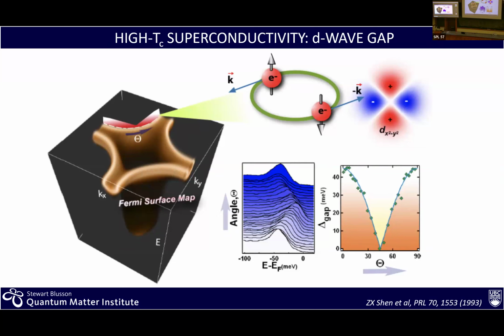And that's the last part I'd like to show you about the past, where again, here is an image of this Fermi surface. And if you want to look at the pairing symmetry with these techniques, you have already been told that the pairing symmetry would have this d x squared minus y squared shape. So large gaps along two perpendicular directions, zero gap or zero pairing along the other ones. Experimentally, here is the chemical potential. Electrons should be present up to there. If you look here in the middle, you see a peak located exactly at the chemical potential.